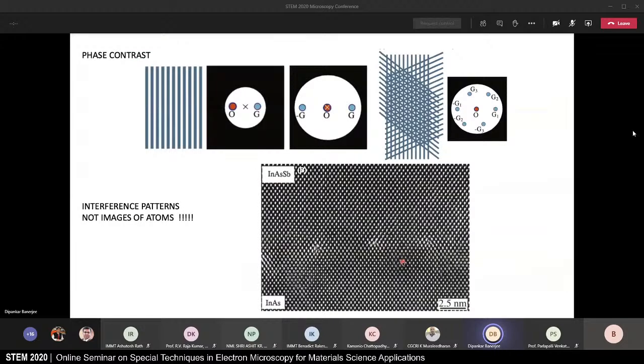And so we have two new techniques that I now have to talk about, or three as we go along. So one is phase contrast. And I talked earlier about putting your objective aperture around the transmitted beam or the diffracted beam. But if you put your objective aperture around the combination of transmitted and diffracted beams, then you get phase contrast in the microscope, and the interference patterns that you get represent the position of the atoms in the microscope if you do it correctly. And I'm sure people are going to talk about this in more detail later, but you can see an example of atomic resolution using such a technique with these defects that you see, dislocations over here.